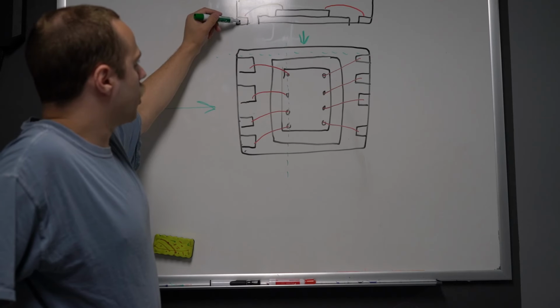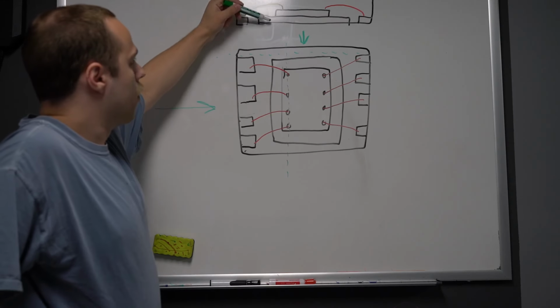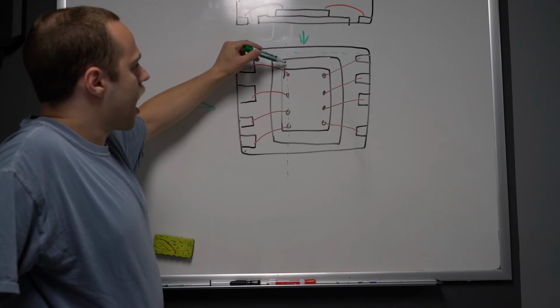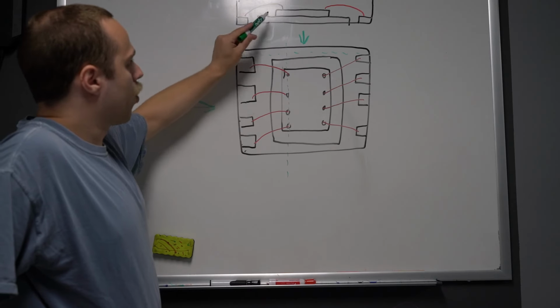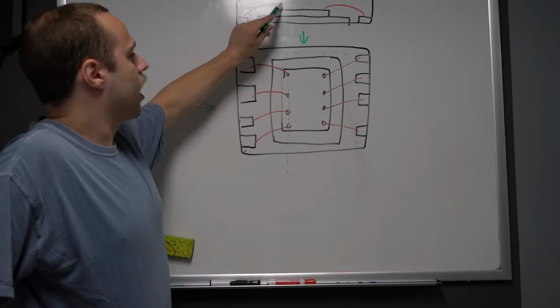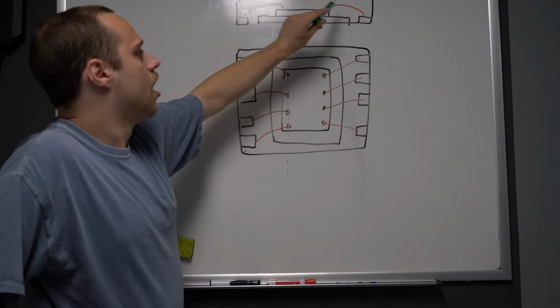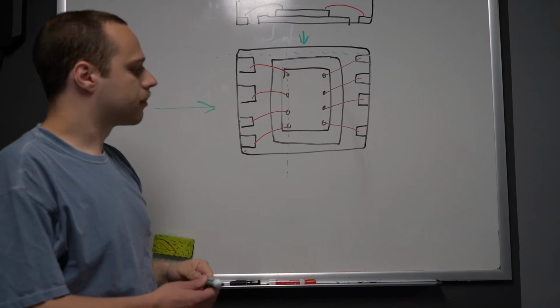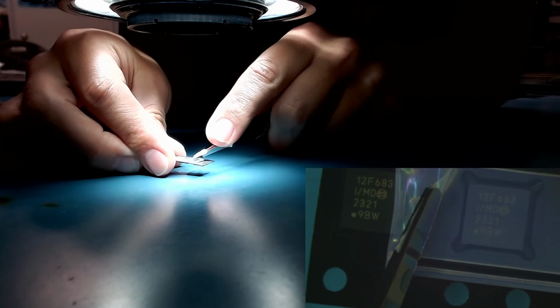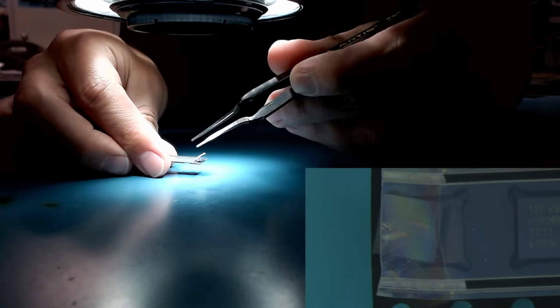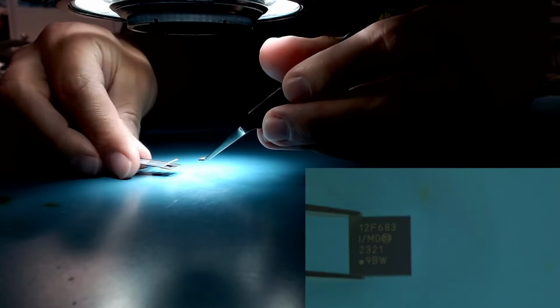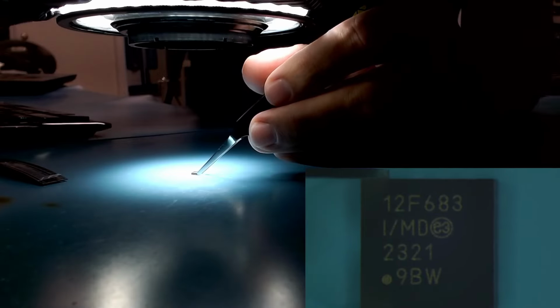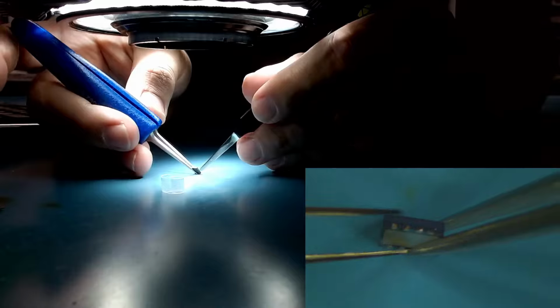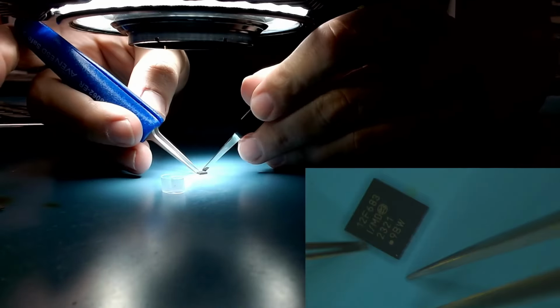This does mean that we're not going to be getting the solder terminals in cross-section, but we are going to be getting the die attach paddle, we're going to be getting the actual silicon, the adhesive layer between them, the wire bonds, and then obviously lots of the epoxy glass filled molding compound. Right now I'm taking one of the samples off of the tape. This is a PIC12F683 in the industrial temperature range, the 4x4 millimeter 8-pin DFN package, date code 2321, and the last line, 9BW, is a lot number or something like that.